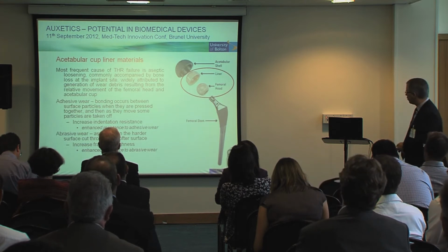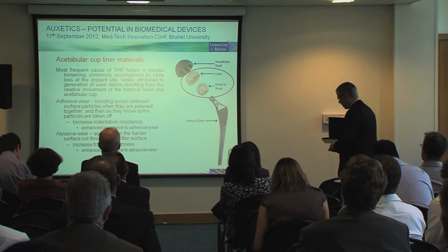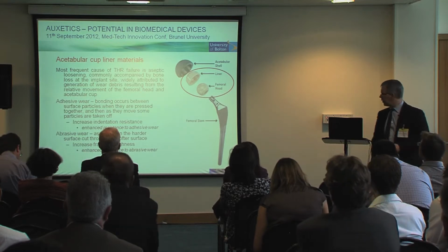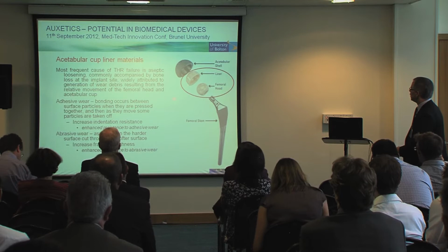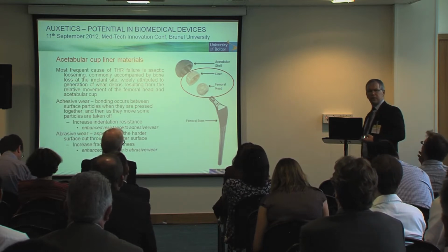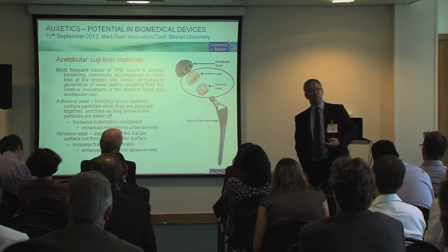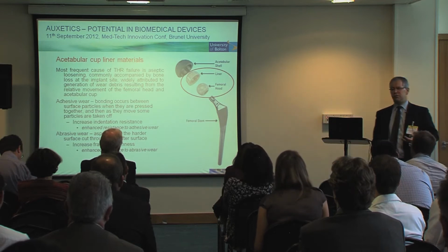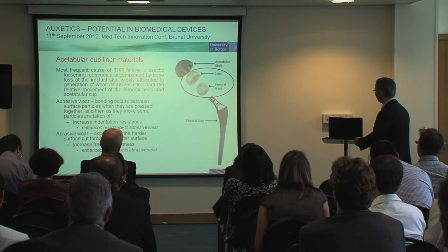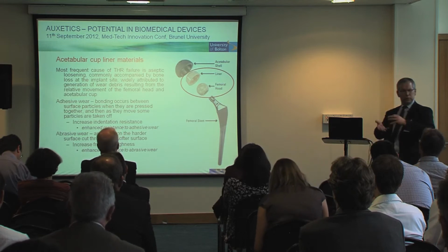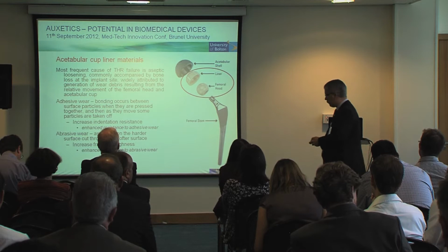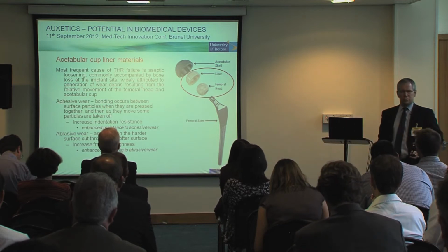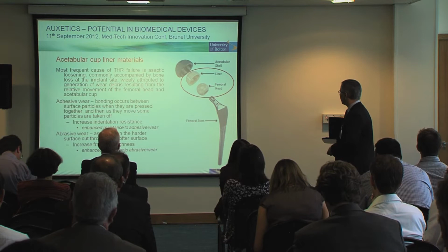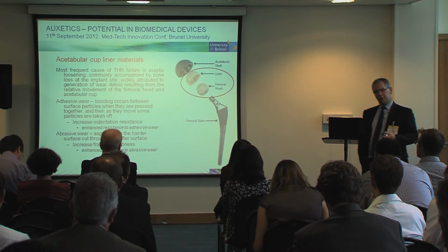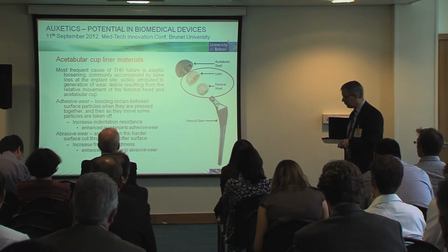Another area that is attracting some attention is in hip implant devices. If we think about the cup liner materials, one of the main sources of failure for total hip replacement devices is aseptic loosening due to the generation of debris as the liner and the head cause wear on each other. So the debris then gets into the body, it causes interactions, which then ends up with loosening of the stem device. So if we could reduce the wear of the liner in some way, then we might be able to lengthen the lifetime of the device.